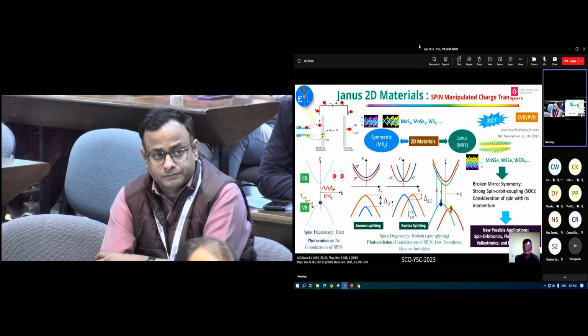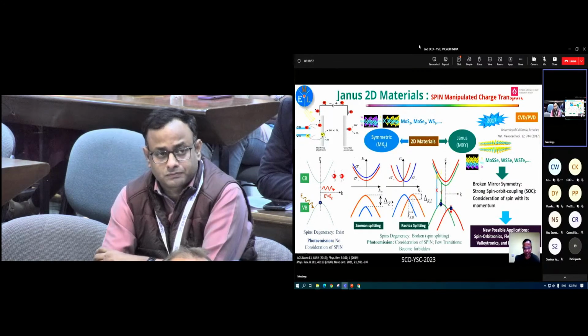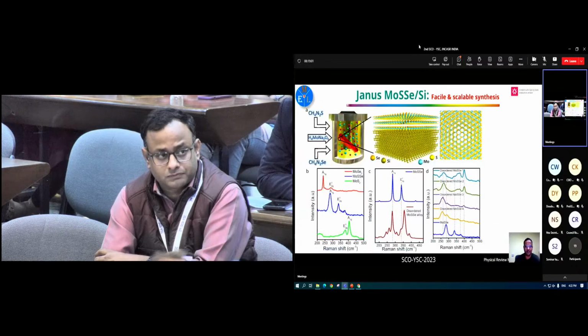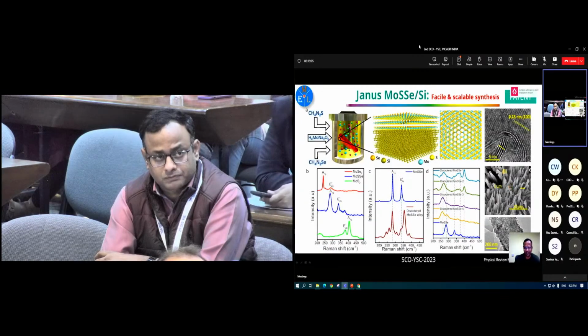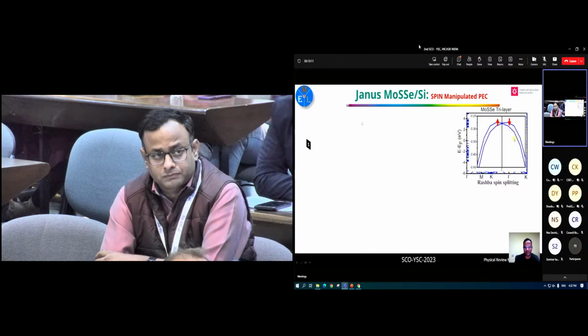So you can have Rashba splitting in the valence band, and in the conduction band you can have Zeeman splitting. Once you use this kind of system like MoSSe, they don't have a magnetic element, but still due to the Rashba splitting, they show spin manipulation under the magnetic field. So we first addressed the issue of the synthesis of MoSSe. We recently filed a patent to synthesize Janus MoSSe in a facile way, and then we did the photoelectrochemistry experiment. This is the band structure.